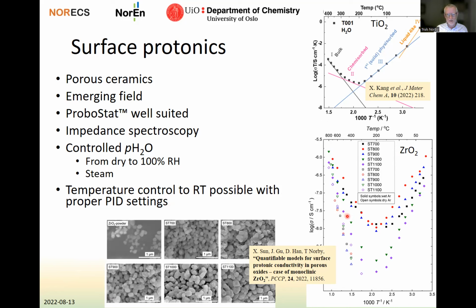Here is another study on zirconia, showing the different conductivities as a function of inverse temperature again, on samples sintered differently, therefore with different grain sizes and porosities. And it is interesting to see how conductivities can vary by many orders of magnitude as a function of temperature and microstructure of the sample. These measurements are done in collaboration between Suzhou University in China and Oslo University in Norway.